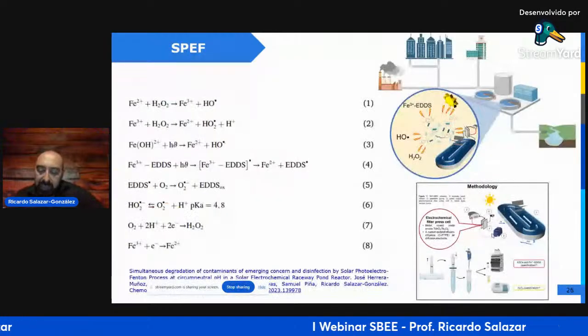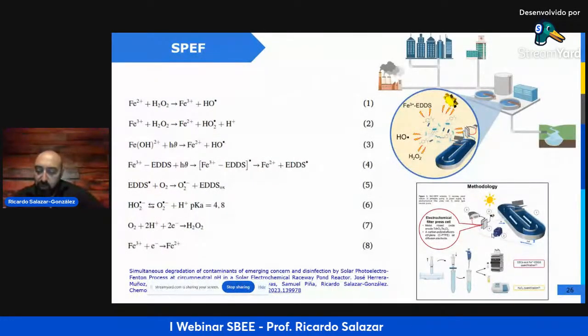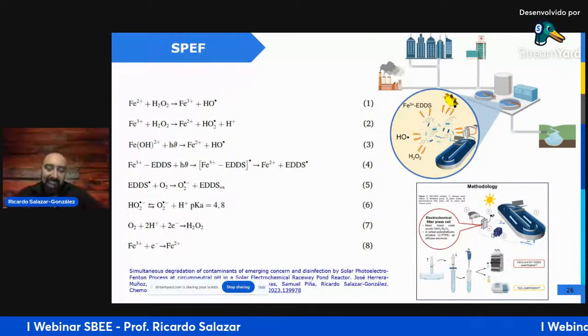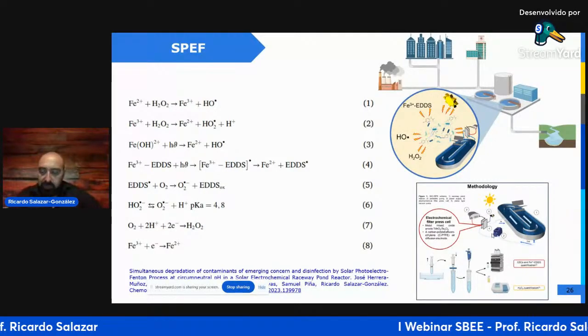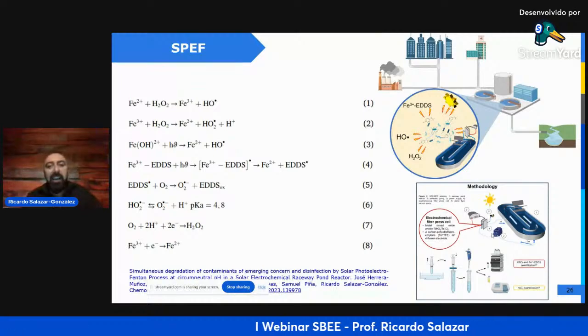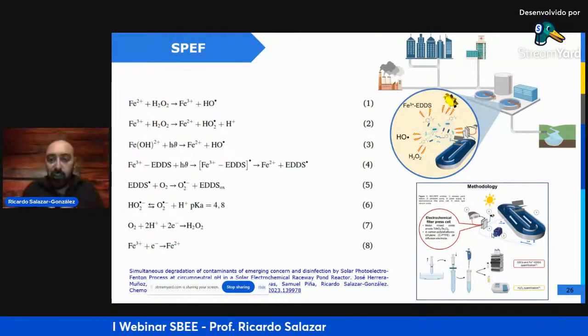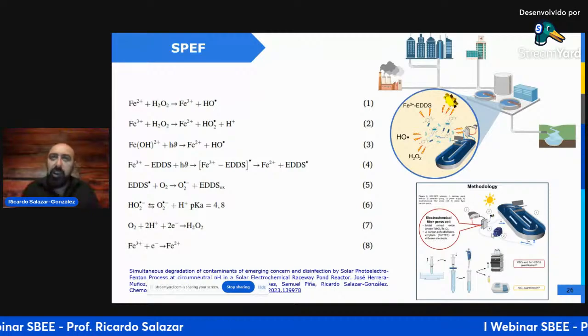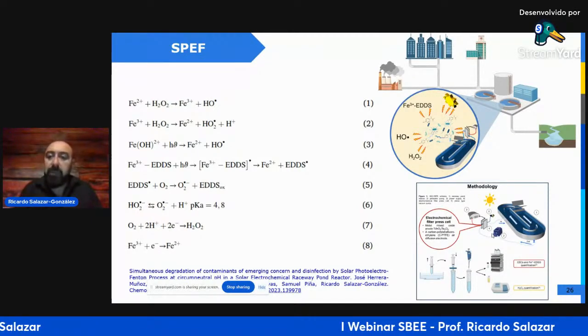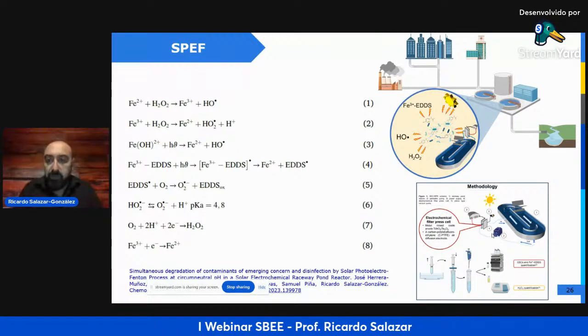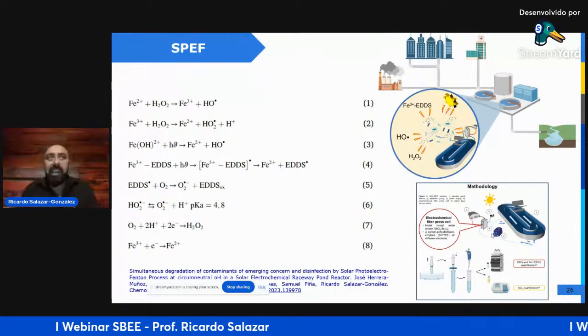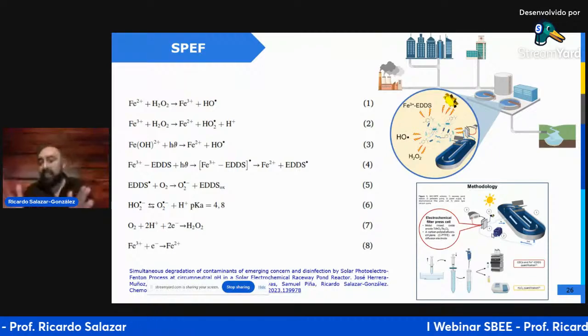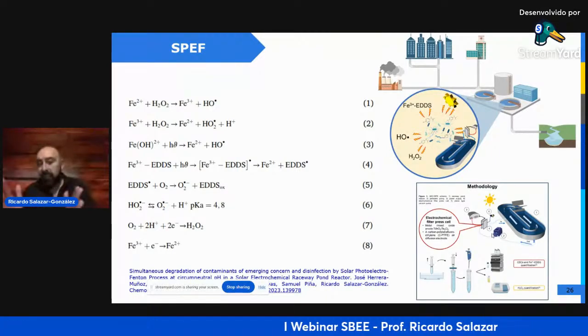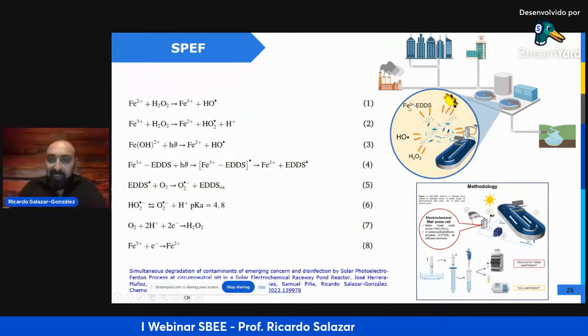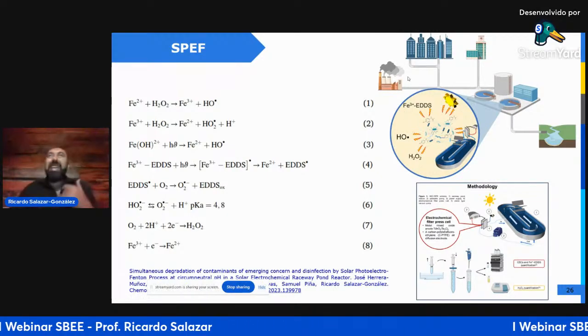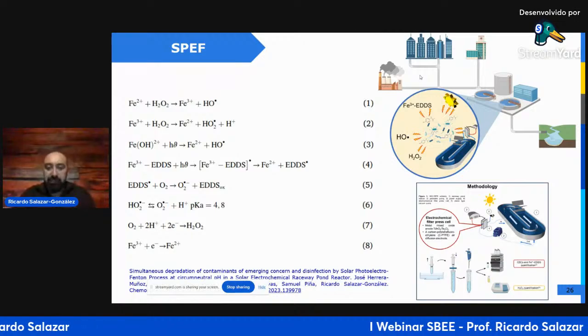When we use the system in a real treatment of a real wastewater, we have a problem with the electro-Fenton process. The main problem is that we need iron in solution. The pH of a real wastewater, for example, from a municipal wastewater treatment plant, is between 5 and 8. At this pH, the iron precipitates, so we can't produce the Fenton reaction.